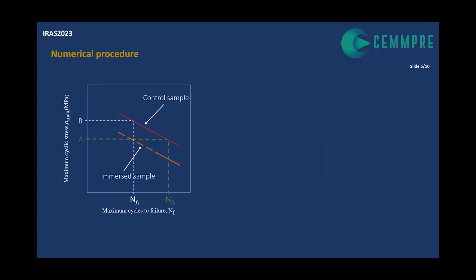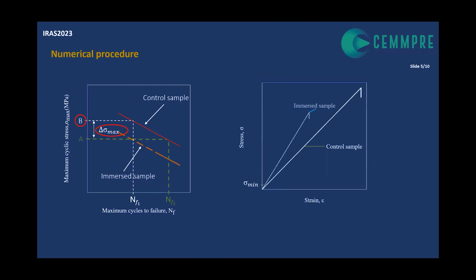So how can we acquire the SN curve of an immersed sample from the SN curve of the control sample? Well, the fatigue life of the immersed sample, NF1, can be obtained if we apply the loading conditions B in the control sample's SN curve. But how can we get the loading conditions B? B can be obtained by knowing the value of delta sigma max, which can be estimated using an energy-based consideration from the stress-strain curves, which I showed previously.